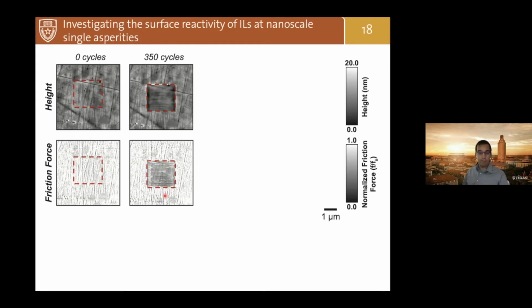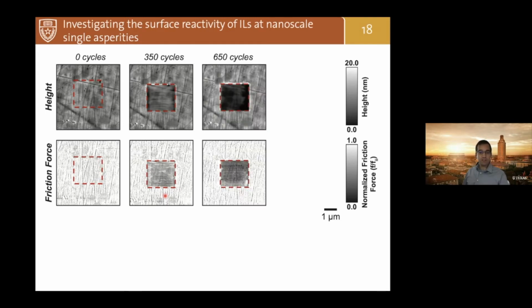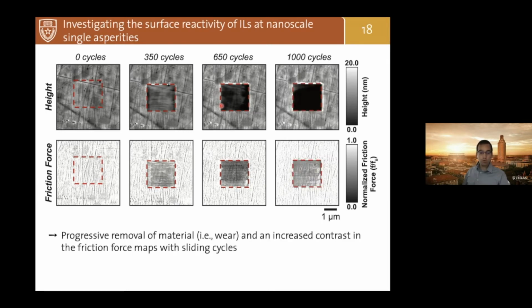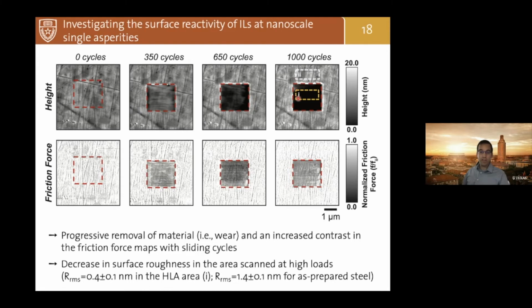force measured by AFM. And again, we can increase the cycles in the inner part of this image, where we apply very high load. So we perform 650 cycles inside this area dashed in red. And again, we are removing more and more material. So there is a progressive removal of material, and at the same time, we also have a decrease in friction. The area that was scanned at high load was actually getting much smoother as measured by RMS roughness.